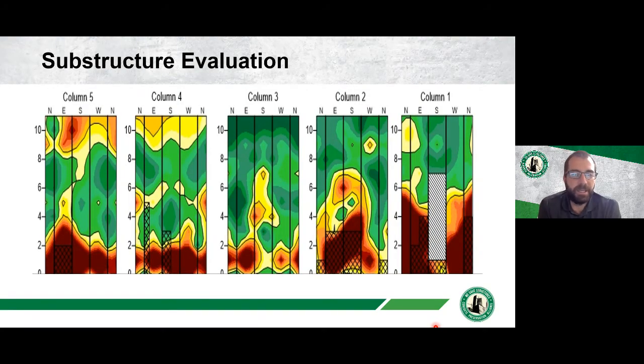Here are some columns where we measured corrosion potential, and you can see where we've identified the active corrosion on each column or pile. You can see where the delaminated concrete is by these hatching marks. And by going through all those piles, we could classify which piles were actively corroding and which piles needed to be repaired or preserved for that structure.